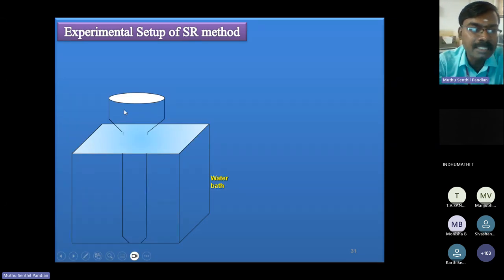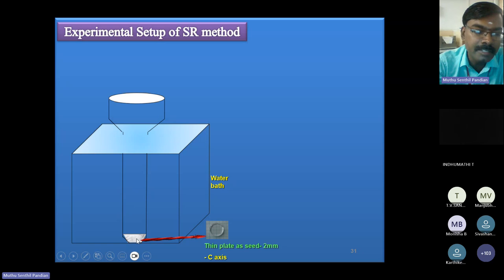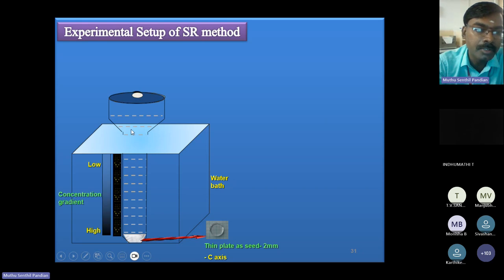So the experimental setup of this SR method consists of the glass ampoule, and this glass ampoule is kept inside this water bath. A thin plate-like seed crystal is mounted at the bottom of the glass ampoule, and then we have to pour the saturated solution inside the glass ampoule, and we have to make a small hole at the top of the glass ampoule. And then we have to apply two different temperatures, one at the top portion and another at the bottom portion. After a few hours, due to gravity driven concentration, all the solute molecules approach the crystal surface directly. So the crystal surface attracts more atoms very easily. So in this conventional SR method, the concentration at the bottom portion is very high compared to the top portion.